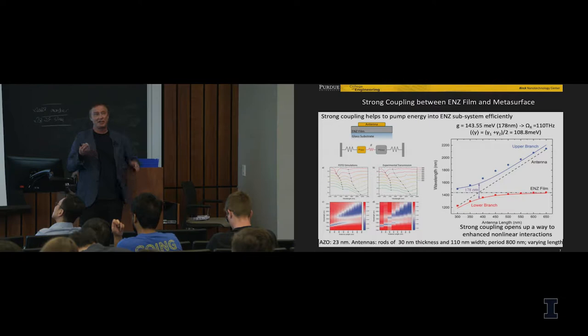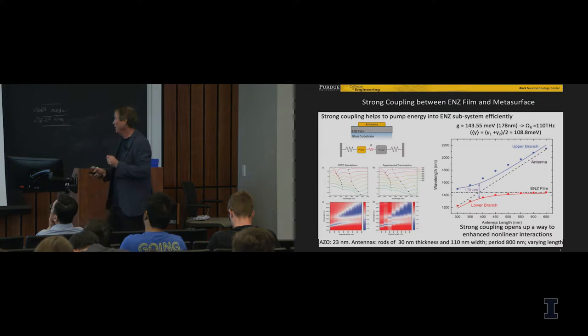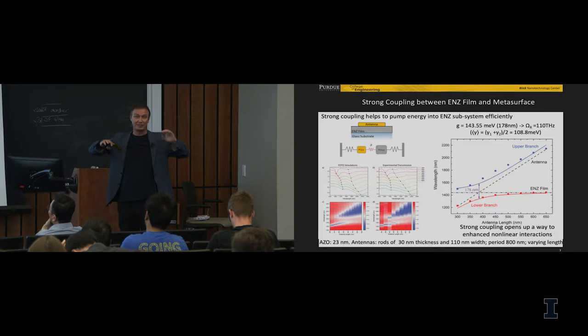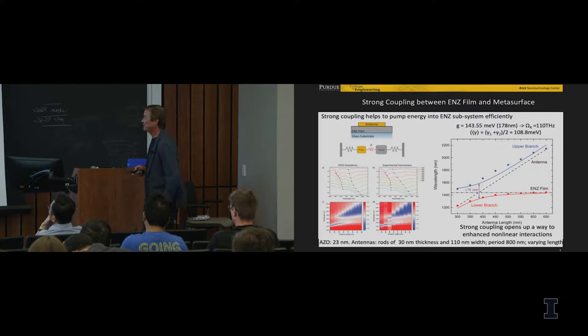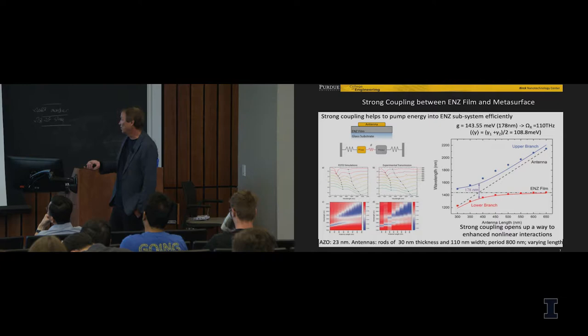In this case, the problem we are trying to address: if epsilon really is small, if you think like engineers in terms of impedance matching, it means that the impedance really is mismatched. It's really hard to get light energy inside of a material where epsilon is close to zero because it's a huge impedance mismatch. But if, however, you place antennas on top of this ENZ material, which is basically a metasurface, that's what a metasurface is about, just a bunch of antennas, then these antennas couple light inside of the ENZ material, and that strong coupling actually opens a way to enhance nonlinear responses.